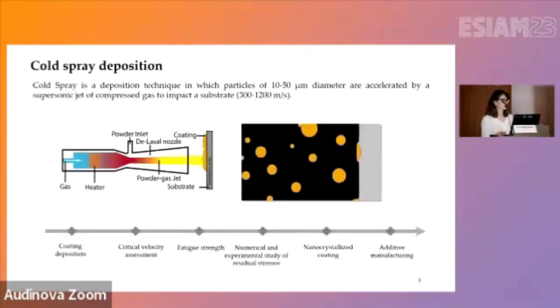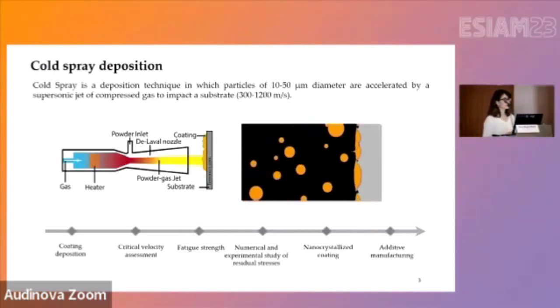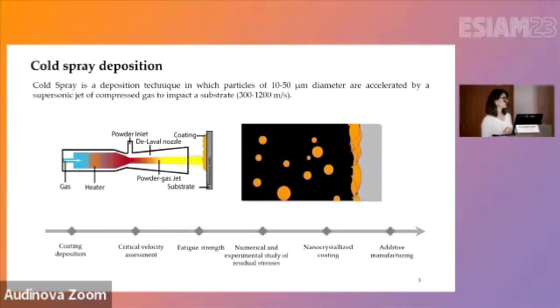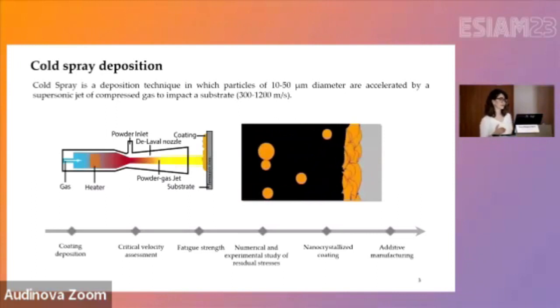It's called cold spray. Cold spray is a non-thermal deposition technique in which small particles are accelerated by a supersonic gas. They impact the substrate at very high velocities, and because of the high kinetic energy, they get severely plastically deformed. They adhere to the substrate, and then they would build up the layer.